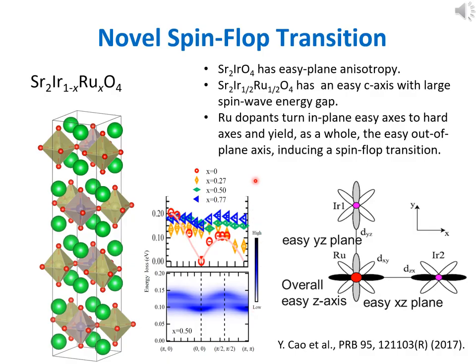I don't have time to detail the physics of this quasi-2D material. In short, the undoped compound has easy-plane anisotropy due to pseudo-dipolar interaction. Ru dopants effectively change the sign of the pseudo-dipolar interaction and tilt the easy axis out of plane, inducing a spin-flop transition.